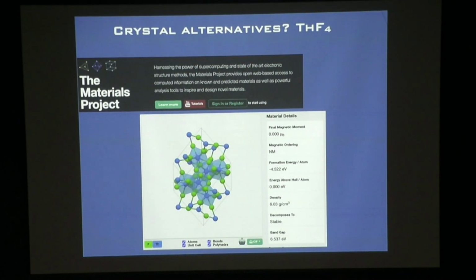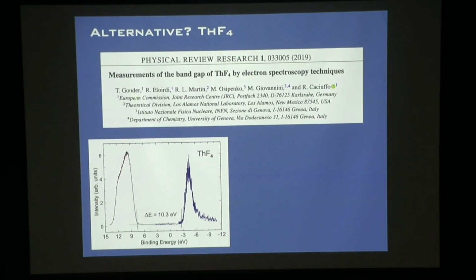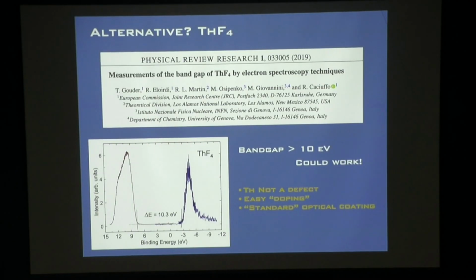However, a couple of years ago, mostly led by Richard Martin from what I can tell, some people reevaluated this. They did new DFT calculations that led to experiments, and the band gap's actually 10 eV. It's not 6.5 eV. If you talk to DFT people, they're like, yeah, sure, that sounds right. But for us, that's a really big deal. So we would love to do this. This could solve a lot of problems. But growing a thorium fluoride crystal is a lot of work.